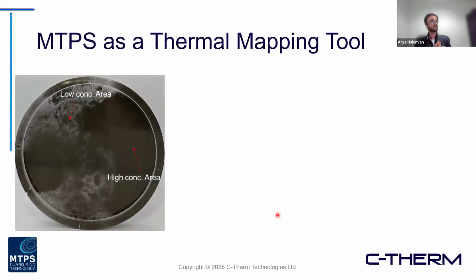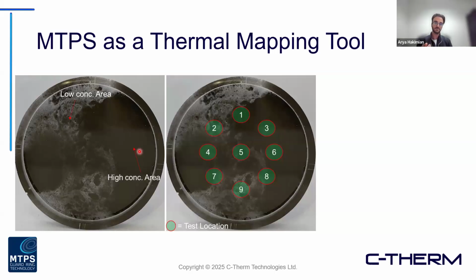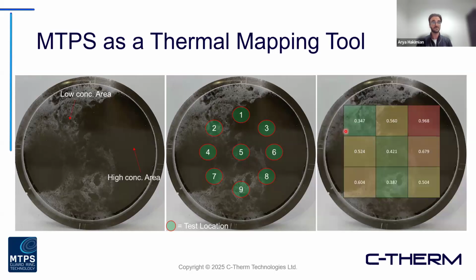And what this is, essentially, if you have a material, so this was an epoxy filled with a conductive metal nanoparticle, we can see, with just this example, very obviously non-uniform. We have areas of high concentration of the filler, areas where basically it's just the neat polymer, very visibly obvious in this case. But the idea that we want to show here is that with the MTPS being a single-sided sensor, one of the nice advantages here is that we can actually place it at different locations across the surface of the material. And then very quickly, start to finish, cool down time, data collection, about 60 seconds per spot, we can get some effective thermal conductivity values and, again, quantify and relate them back to that filler